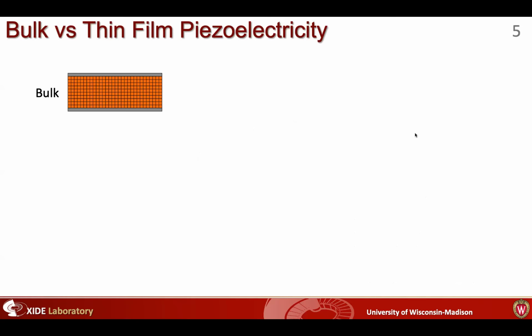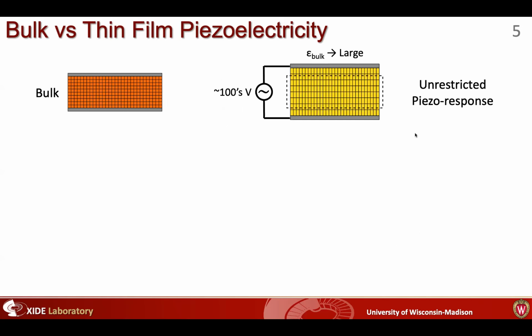When using a bulk piezoelectric material, typically your electrodes cover the entire top and bottom surfaces. That way, when you apply your electric field, you get this unrestricted piezo response involving the whole crystal. While the strain is large, because of the bulk dimensions, it's going to cost you a lot of voltage to generate the electric field necessary to exhibit the piezoelectric effect.